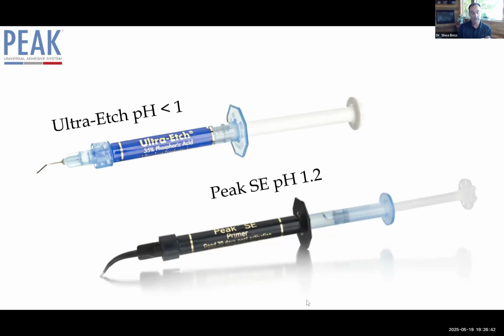Since then, we've come a long way, and we have learned an awful lot, and Ultradent has done an awful lot with Ultra Etch. All those years ago, Dr. Fisher spent an awful lot of time with this. And one of the things that he has done with Ultra Etch is that he has put silica in it, which minimizes the depth that that etch can get inside the dentin. And so it averages between 1 and 2 micron depth of etching into the dentin, and that's really important.